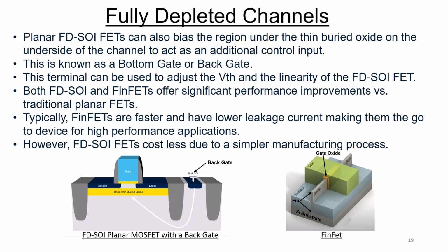Now this planar fully depleted SOI FET can also bias the region under the buried oxide by using an additional contact. And this is known as a bottom gate or a back gate. And this terminal can be used to adjust the threshold voltages and the linearity of the fully depleted SOI FET.